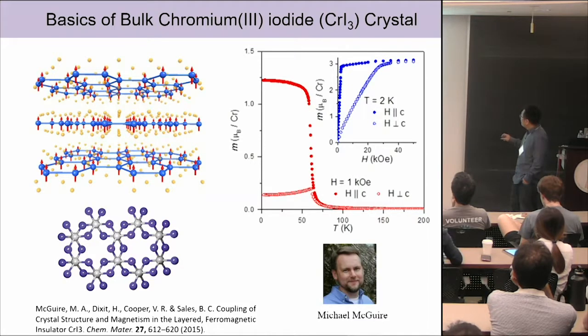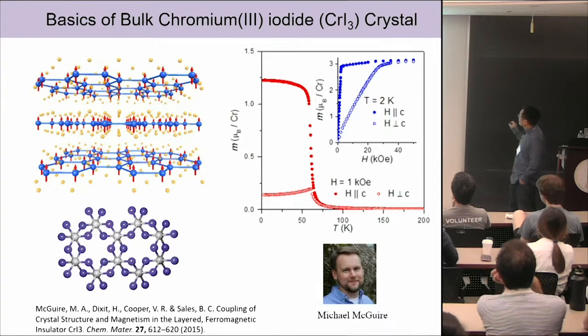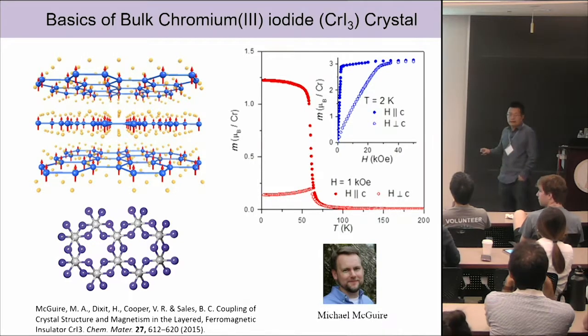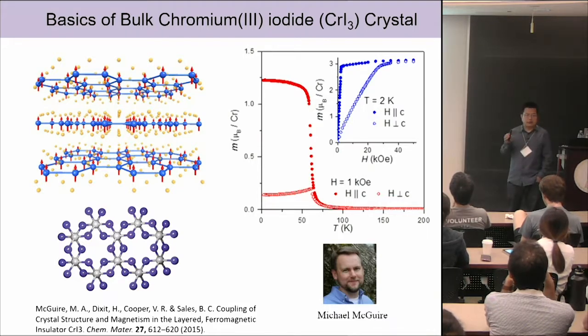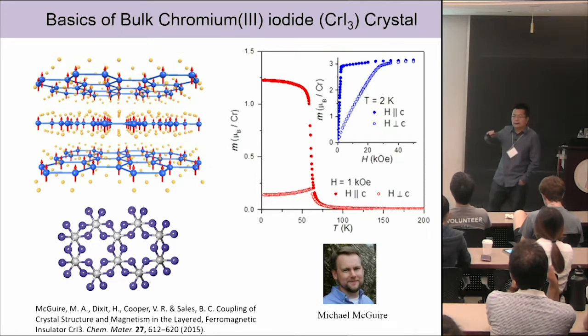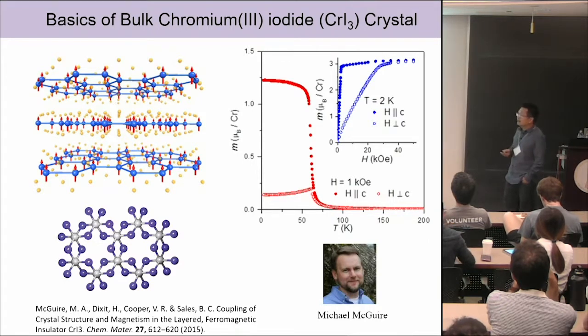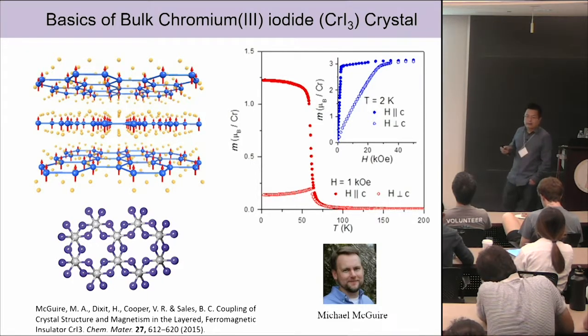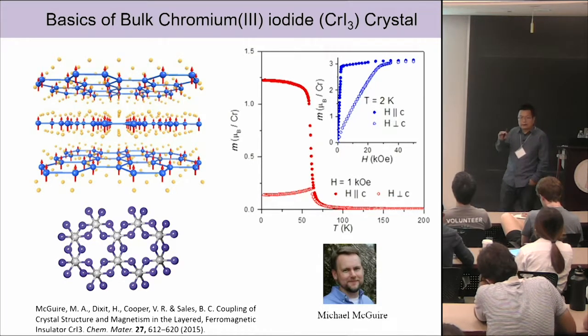My collaborator Michael McGuire initially told me about chromium triiodide. What really interested me was his magnetometry measurements showing this particular crystal has very strong out-of-plane anisotropy. This is very important — we all know from the Mermin-Wagner theorem that if the exchange interaction is isotropic, there's no long-range order in 2D or lower dimensions. So we need anisotropy. He also showed the Curie temperature is quite high at 60 Kelvin — good, because when you thin down, the Curie temperature may drop, but there's a lot of room below 60 K. Both were promising signatures.